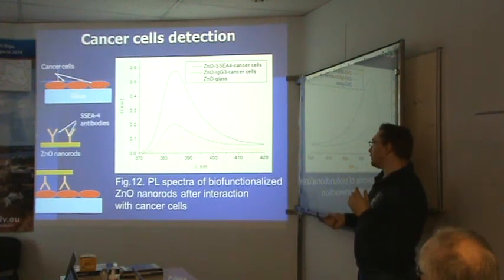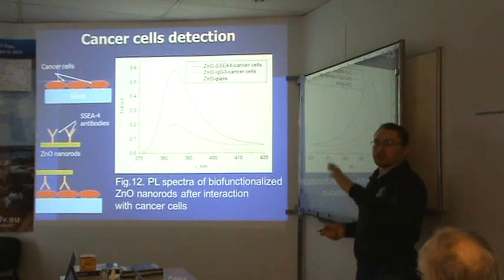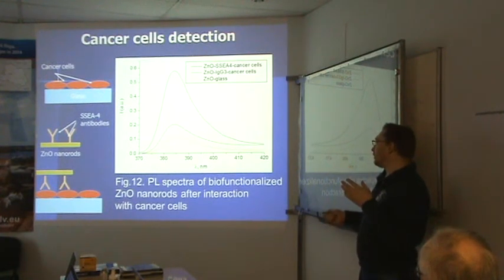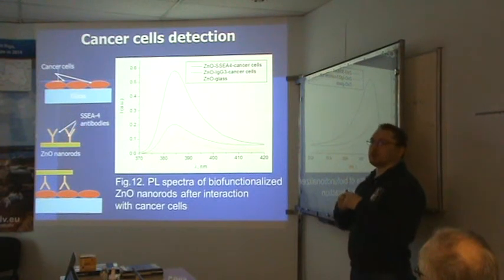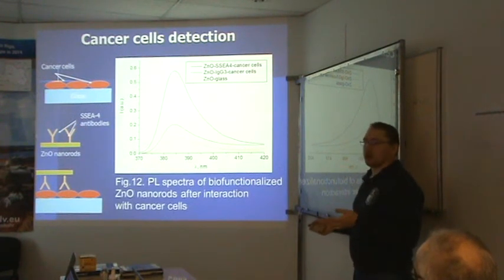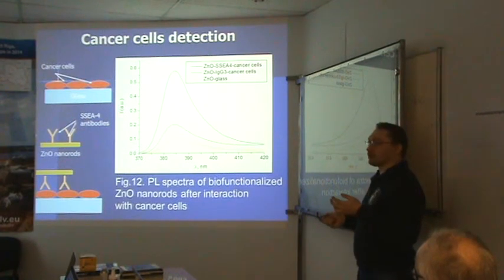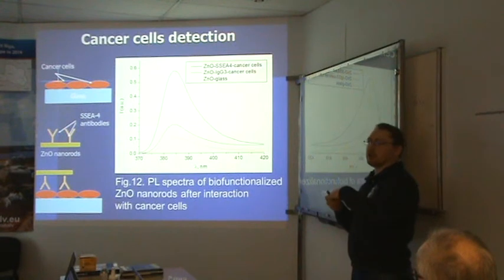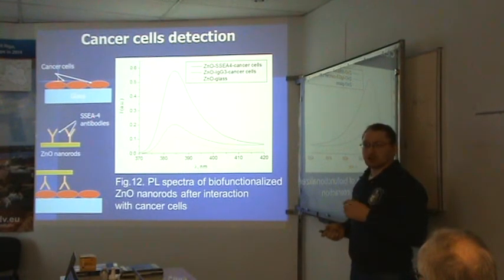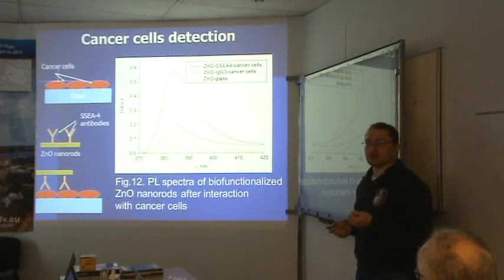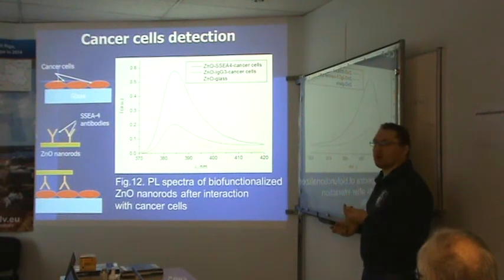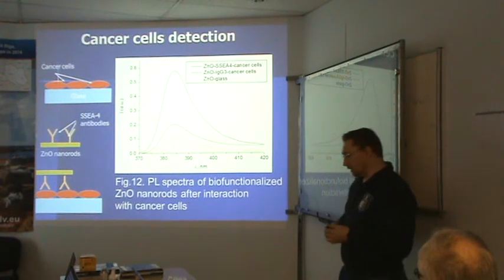You can see that if you use just zinc oxide and wash it and dry it, you have one signal. When you use non-specific antibodies which do not bind directly to the cancer cells, you have a little bit of increase, because probably non-specific antibodies can attach to the glass. But when you use specific antibodies, you have a huge increase of the signal. So using this technique, you can recognize which cancer cells you have deposited on the substrate. We're thinking about the next step, to use this technique for biosensor application for cancer cells.